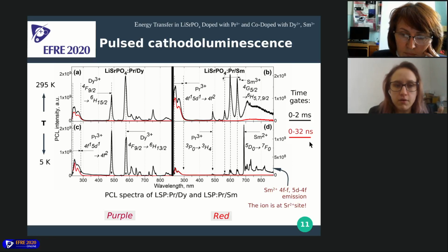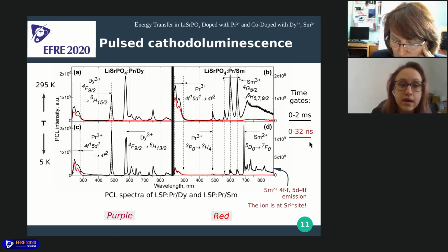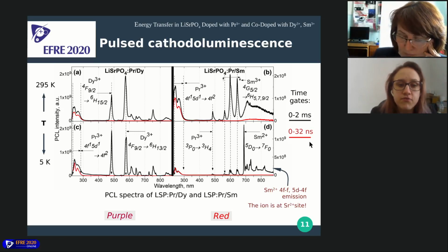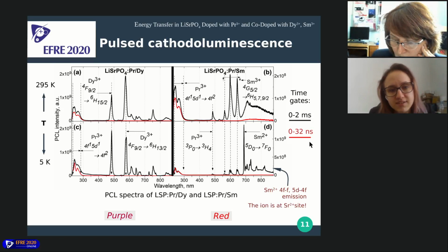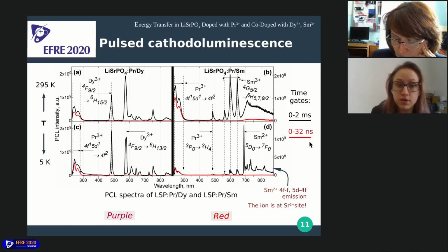And here on the left part, the spectrum for the dysprosium codoped sample. It has these two characteristic spectral lines, as I have shown earlier, and a number of weaker lines in red and infrared region. This is actually what we have expected, nothing special about this spectra, but it is more interesting to look at the samarium codoped sample spectra.